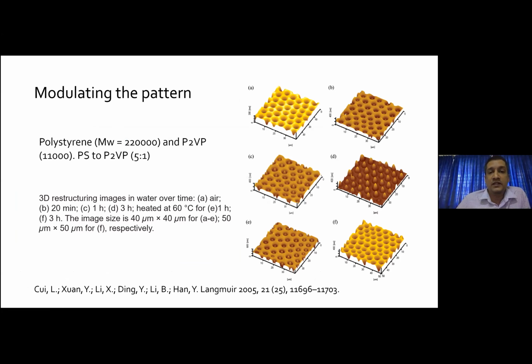What they have done is they tried to see, once you make a breath figure, is it the end of the experiment? Can't we still further modulate the pattern which is formed earlier? So they cleverly designed a work where they took polystyrene of around 2 lakh molecular weight and mixed it with poly 2-vinyl pyridine of 11,000 molecular weight. The molecular weight of polystyrene is very large compared to that of the polyvinyl pyridine, which means the mobility of P2VP is slightly higher. Plus, the poly 2-vinyl pyridine is slightly polar in nature compared to polystyrene. They mixed these two polymers in the ratio of 5:1, then allowed it to make a breath figure.